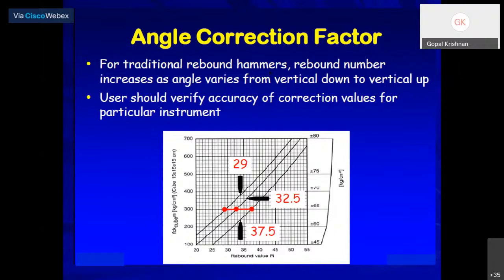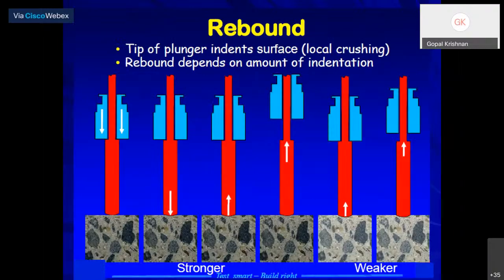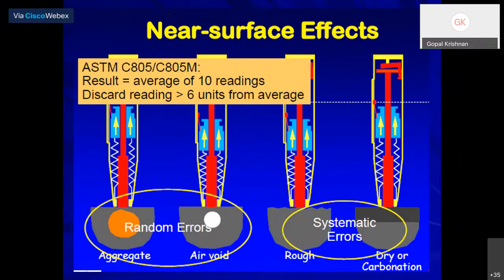As we have shown here, we can see different directions. What is the strength correction we have to make? It is the angle correction. When you are hitting a stronger portion, definitely you will get a higher rebound number. When you are hitting a weaker portion, we will get a lower one, based on the surface. As per ASTM, they take 10 readings and report them.